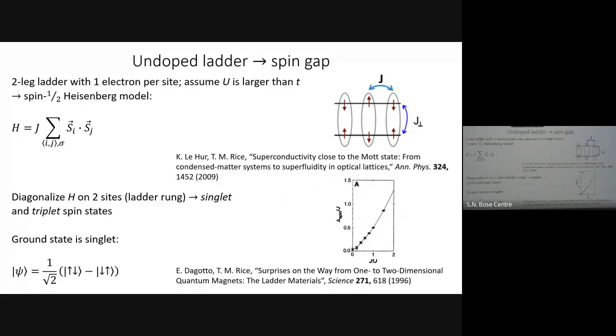So what happens if I have a ladder? It could be the t-J model, and it could be the Hubbard model, but it's exactly half filled with every site occupied by a spin. It turns out that because there is only one neighbor here, it doesn't matter how weak this is, you will form spin singlets here, not an antiferromagnet. Remember, singlet is different: up, down minus down, up.